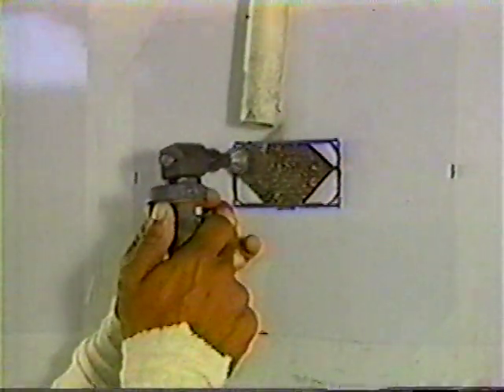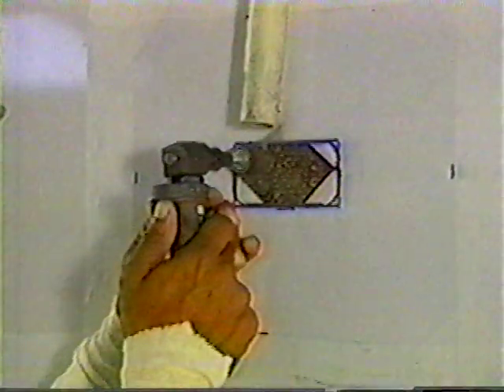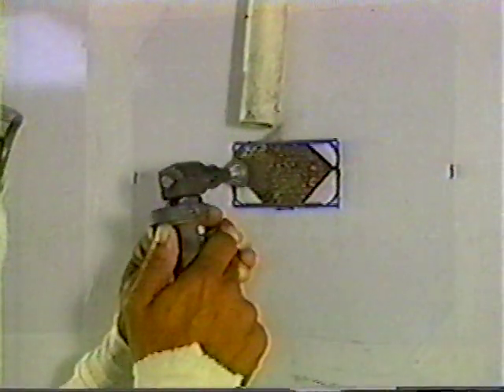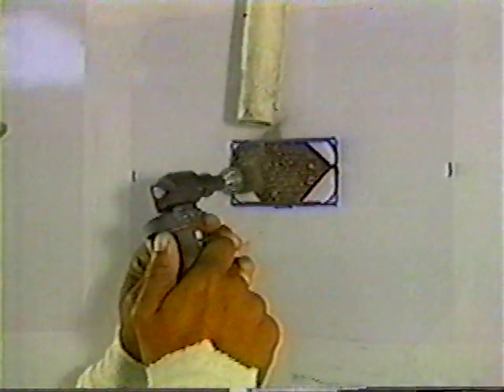Finally, complete the removal of the core and outer skin by using a barrel grinder to grind to the corners of the repair area, removing all loose particles, cracks, and delaminations. Next, carefully grind down only the peaks of the dried adhesive within the repair area, without grinding the residue adhesive footprints all the way to the panel, which may permanently damage the composite material.